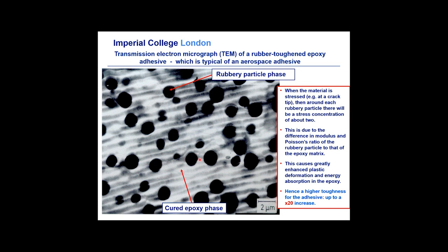And this stress concentration in this area is good because the stress concentration arises from the difference in modulus and Poisson's ratio between the rubber and the matrix, and the stress concentration causes plastic deformation and energy absorption in the epoxy. So the rubber particles really act as catalysts in a sense for plastic deformation in the epoxy, and this can lead to higher toughness values by up to a factor of 20. So it's really very, very impressive.